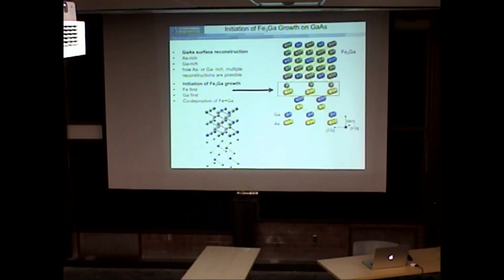Okay, so here we go. We come back to the question. Do I start with an arsenic-rich surface or a gallium-rich surface, how arsenic-rich, how gallium-rich? And when I start the Fe3Ga, if you look at it, it's iron, gallium, iron, gallium atomic layers. Which layer do you want to start with? Do I start with iron first, gallium first, or do I co-deposit iron and gallium? And does it make a difference? So that's one thing we sort of worry about.